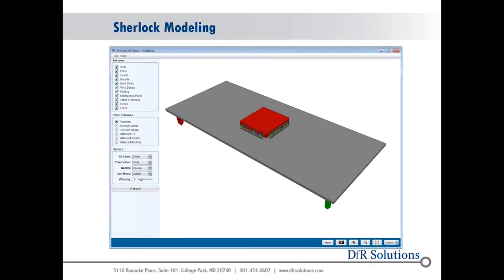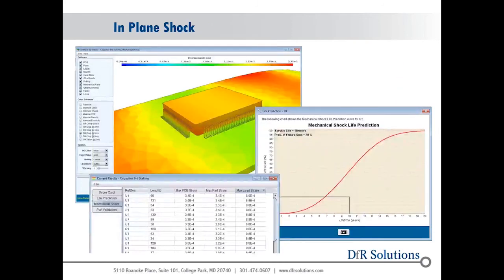This is just a simple model of a ceramic quad flat pack. Again, these parts are notorious for having sort of in-plane type of motions. This is the Sherlock simulation showing that part. This is a shock pulse in the X direction of the board, so an in-plane shock pulse that's causing this part to displace to the right. And you can see these leads are bending sideways.